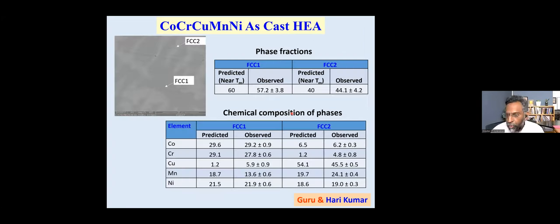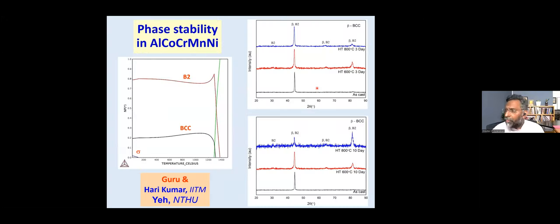And one can do thermodynamic calculations to say how much percentage of these two phases can be predicted and what is the composition of each phase. And you can actually do an experiment and find out the observed phase fraction, 44%. The predicted phase fraction is 40. So you can say, yes, you are reasonably close in terms of phase fractions and in terms of composition of the phases. So one can do this with various systems.